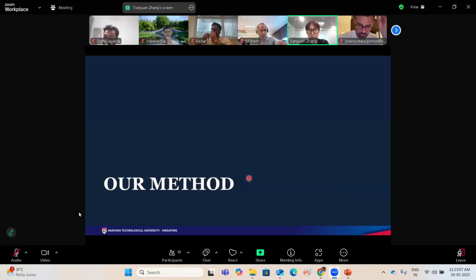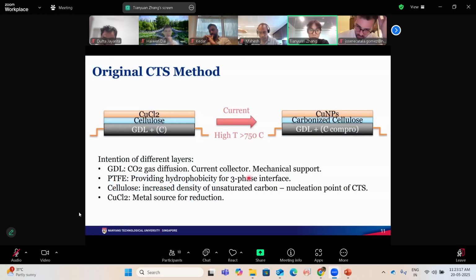And based on this background, we started to think the cellulose layer distribution is a very big problem, so we have to change our previous method. Here is the mechanism of our original CTS method. Basically, we use carbon paper as a substrate, and after we applied a relatively high CTS temperature, above 750 degrees, the cellulose will be carbonized and provide a high density of defect sites, which allowed copper chloride to be reduced into copper nanoparticles.